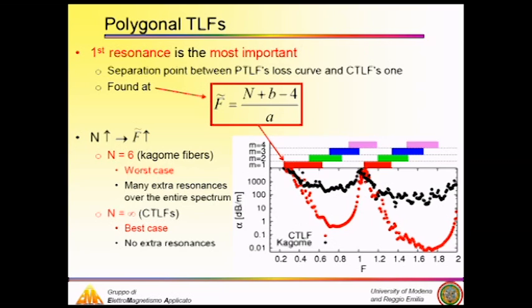Well, it's not difficult to prove that the first resonance is found at this normalized frequency. And since A and B are fixed for a waveguide, we can conclude that in order to shift this extra resonance toward higher frequency or out of the frequency range of interest, it is essential to increase the number of the sides in the polygons. So now we can understand the reason for the difference between circular tube lattice fiber and Kagome fibers.